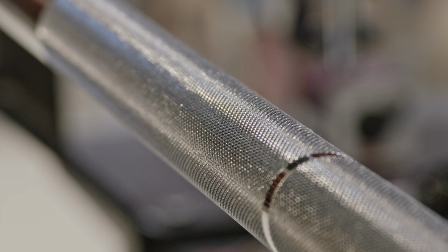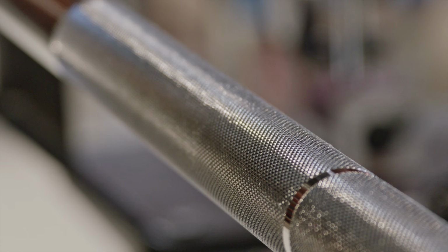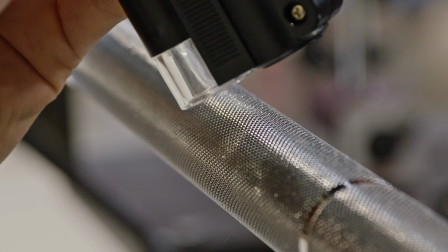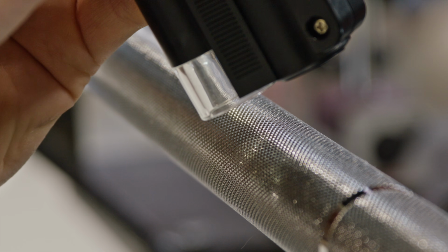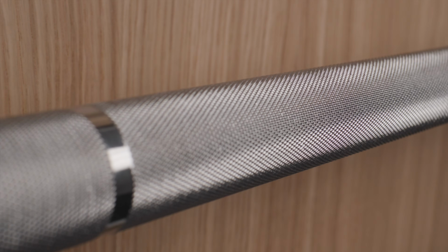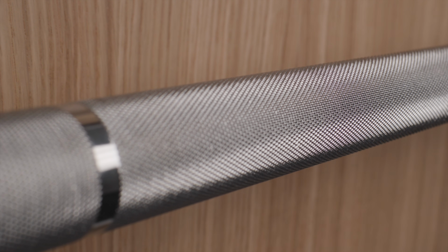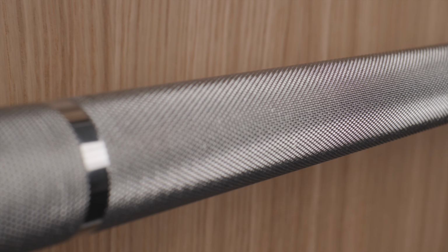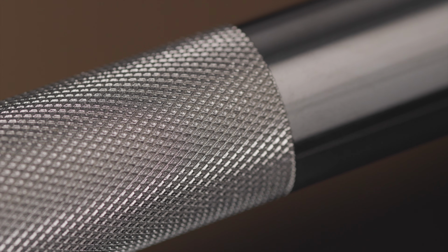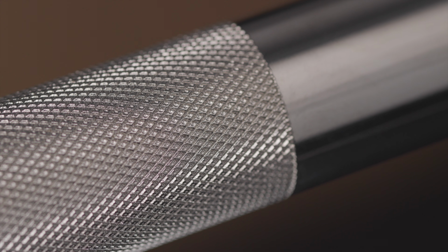And then how hard you squeeze the bits into the shaft. Higher tension creates higher peaks and pointedness. And of course, how sharp the bits are. They have to be replaced after only a few bars because they get worn down by how hard the Eleiko steel is. And a pyramid knurling is the result of high tension and many deep revolutions with sharp tooling. The material is squeezed all the way to form sharp peaks. A volcano knurling is done with moderate tension and rotations, so the steel is not pushed to a full point, and that leaves the center kind of depressed.